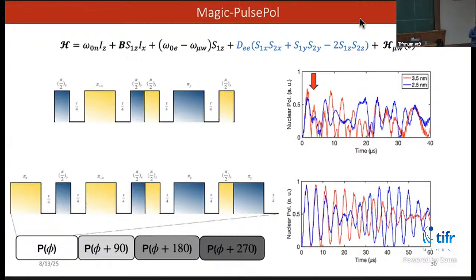Yes. But then why is it dependent on, I mean, it should be irrespective of whether it's the continuous wave or the pulse, right? Why is it dependent on when you are pulsing, the efficiency is going down, but seems to not matter? When we are pulsing, we are using a slightly different method as compared to continuous wave. In continuous wave, one uses a technique called solid effect DNP, where the irradiation is at a certain offset, and that offset is the nuclear Larmor frequency. So that's a different way of transferring as compared to the pulsed technique. I see. Yes. If you see the final Hamiltonian, the final effective unitary transformation is the same, but how we reach that effective Hamiltonian is different for CW versus pulsed technique.